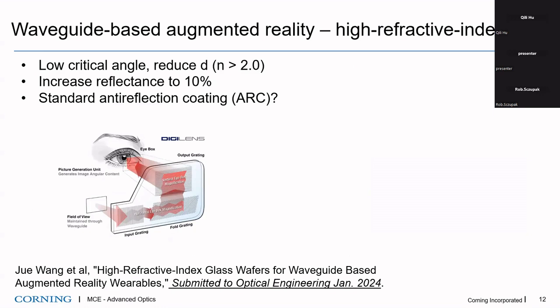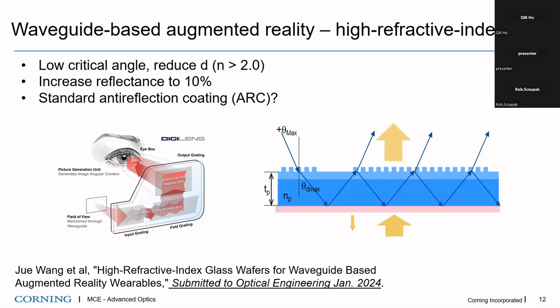Now another thing, another AR. We used to call anti-reflective coating AR, but now augmented reality is also AR. This AR basically requires a high refractive index, which has many advantages. So Corning makes the index higher, greater than 2, for this application. But as the index increases, we know the reflection also increases. For a single surface of glass, it's typically 4%, and this goes up to 10%. So we do need an anti-reflective coating. We call it ARC, right?